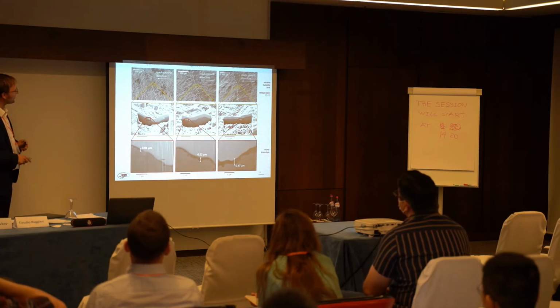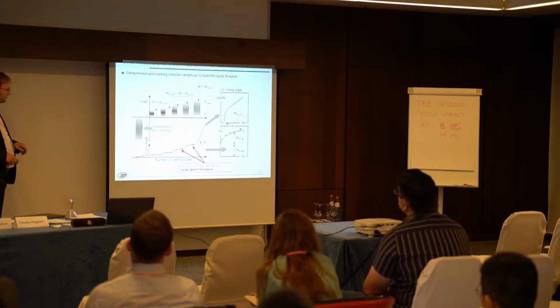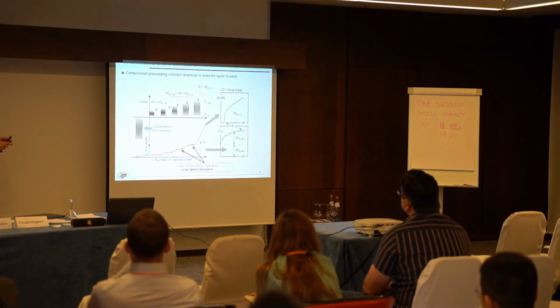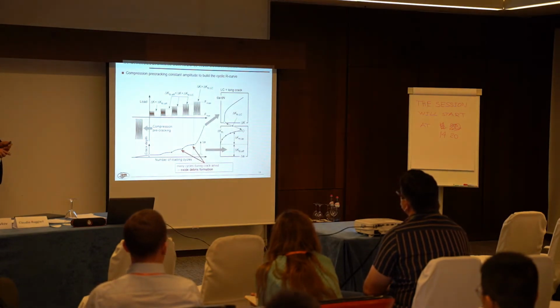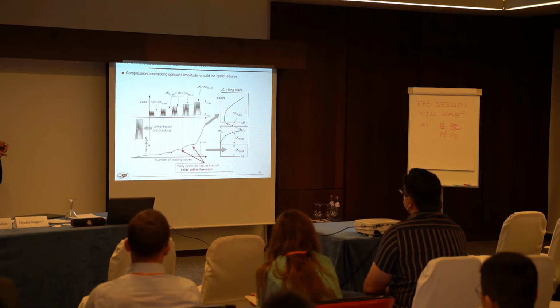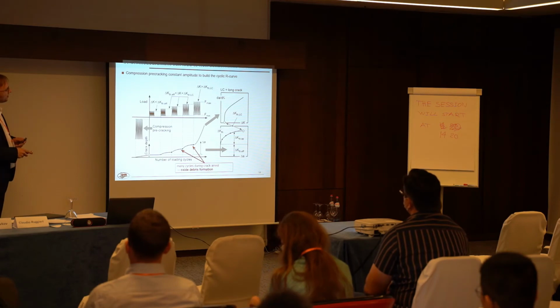Here we have an example of how we can measure the thickness of the oxide debris with focused ion beam, and here we can observe different oxide debris thicknesses after application of different numbers of underload cycles. This is a cyclic R-curve measurement technique of cyclic compression precracking, and this is here just to say that in each step of producing the curves, there are many cycles applied where oxide debris is produced. So actually in steels, the long crack threshold obtained by this method can be non-conservative.